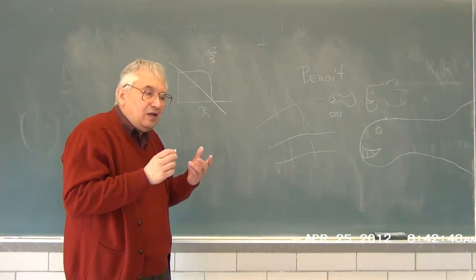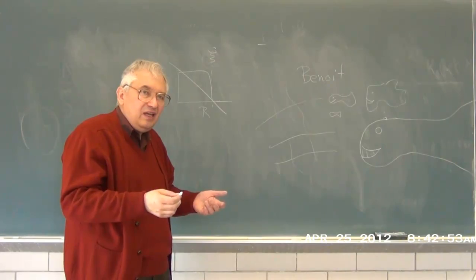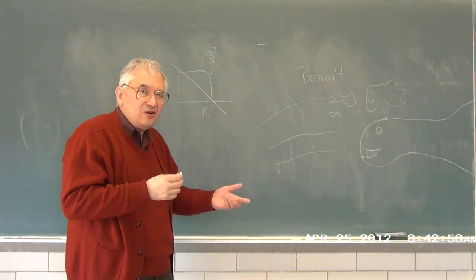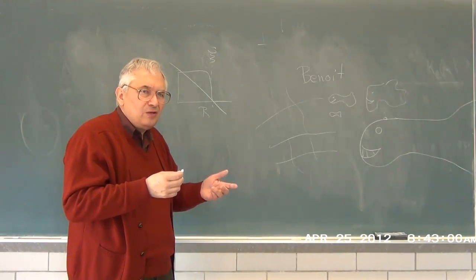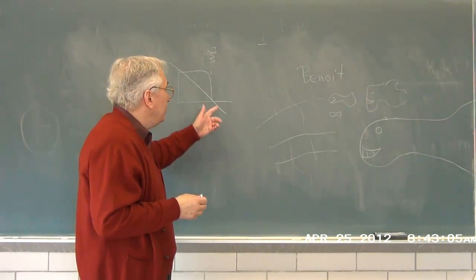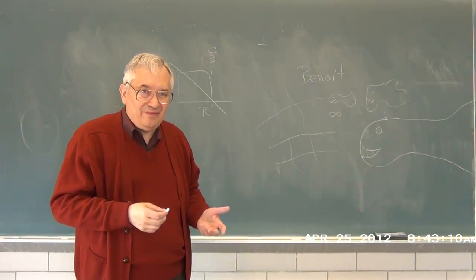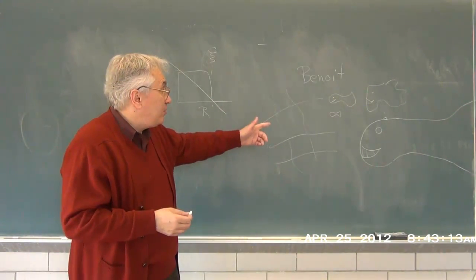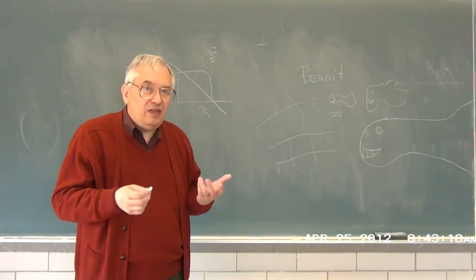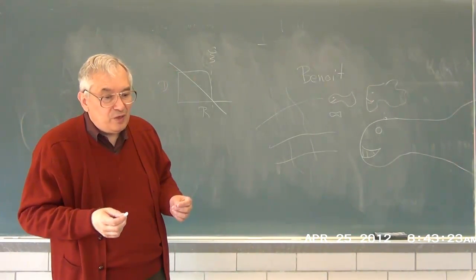Yes, polymer solutions do a certain amount of sieving, and therefore, in some systems, the small particles move faster. In some systems, the large particles seem to move faster. Small is what is usually the case. However, you certainly do not find a blockage for particles above some size. And therefore, this picture is simply not sustained by studies of the diffusion of probes through polymer solutions. The experiment has been done.